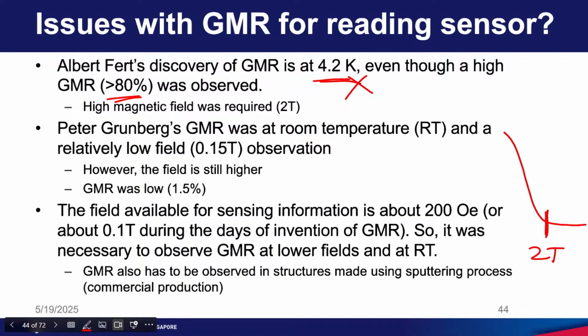Whereas, I told you that in a hard disk we are receiving magnetic field of the order of 200 oersted or 300 oersted. So, this field is too large. For about 200 oersted you may see a very small change somewhere here, which is not very useful. Then if you look at the other group's data, Peter Grunberg's data, it is at room temperature, that is good. It is also at low field, very good, but the GMR was not very high, it is low. So, these are some problems, and the other problem is like you have two ferromagnetic layers.